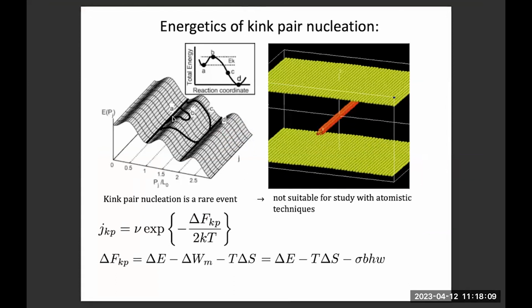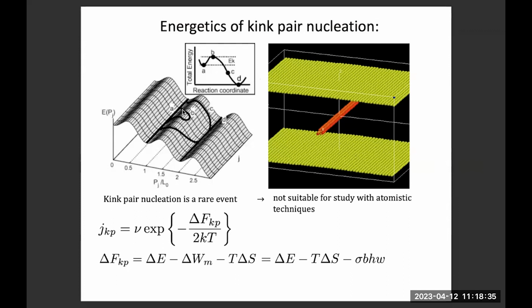So here you can see a better representation of kink. Our initial dislocation is at A, and the dislocation wants to go to lower energy states. Firstly, it creates the edge parts, which are, let me try to annotate, these are the edge components. Then we have kink formation here. Then this kink goes to the lower energy state. Then this part goes to this energy state. These are all kink formations. And at the end, our screw dislocation will come to lower energy state. So this formation is called kink pair nucleation.